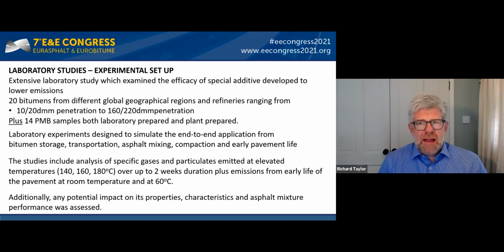And we designed our lab experiments to simulate the end-to-end story. So we had some tests that were focused on the headspace in bitumen storage, some of them during the transportation of bitumen stage, the asphalt mixing stage. So we had asphalt mixers that were instrumented to measure the emissions during compaction, similar with a roller compactor, and then also with slabs of material during their early pavement life.